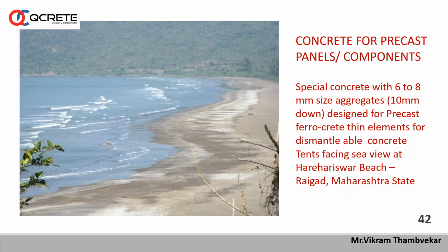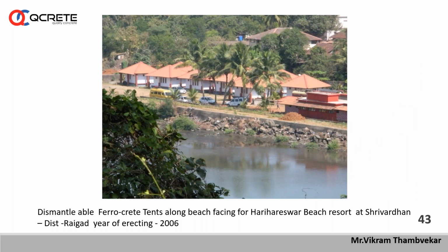Here is another slide I am putting up to show some RCC panels or components cast as precast units. Concrete for precast panel components used special concrete with 6 to 8 mm size aggregates, that is, below 10 mm aggregate size, with a proper design for precast ferrocrete thin elements for dismantleable concrete tents facing the sea at Harihareshwar Beach Resort at Raigad. This is very important to mention because all these elements are very thin. They have only 35 mm thickness. This is a view of our resort where all these concrete tents have already been installed and are under use for the last 13-14 years.